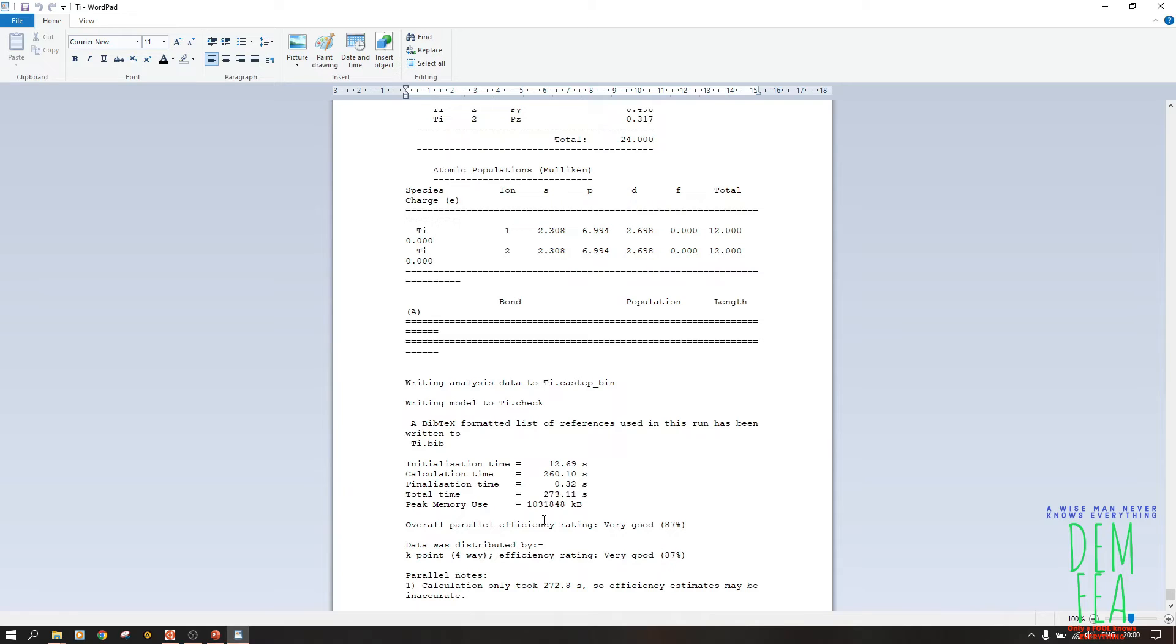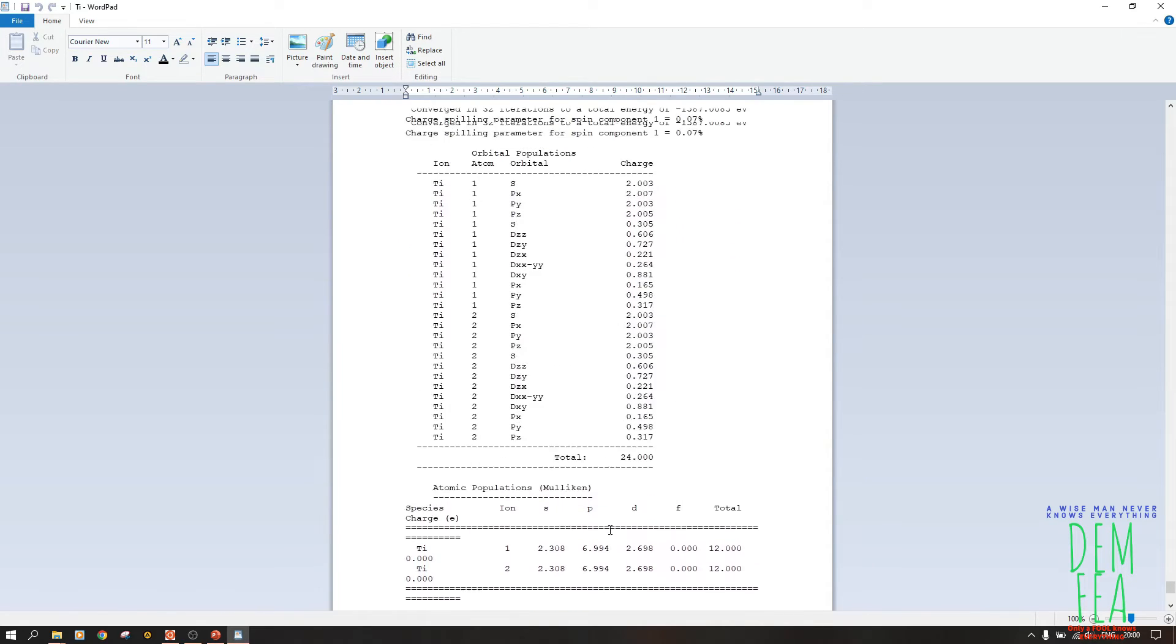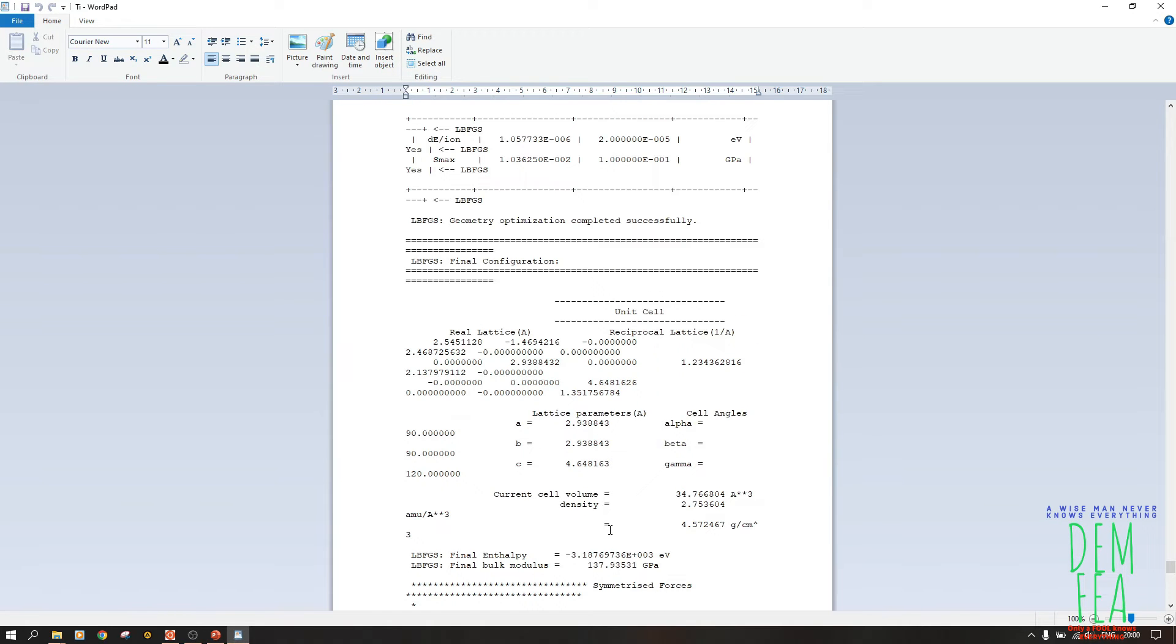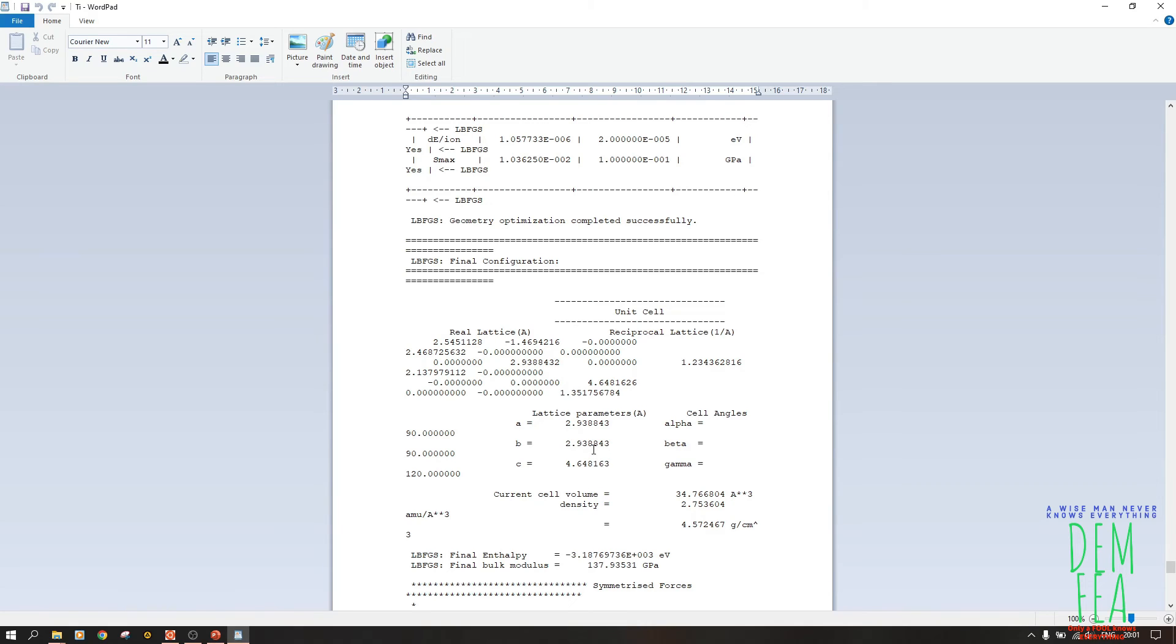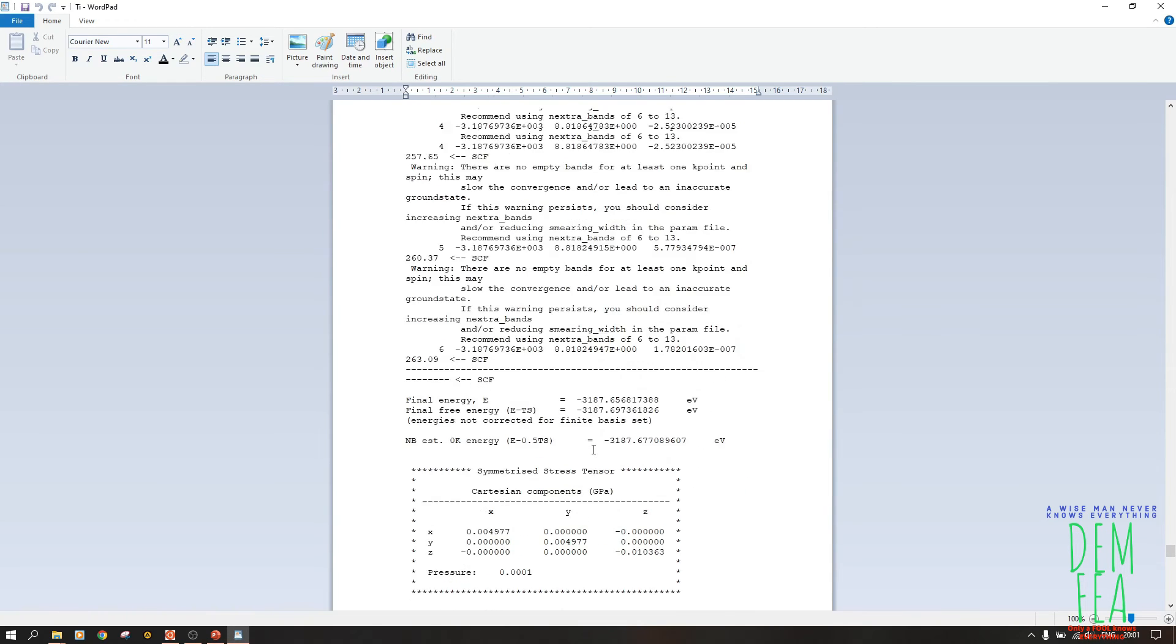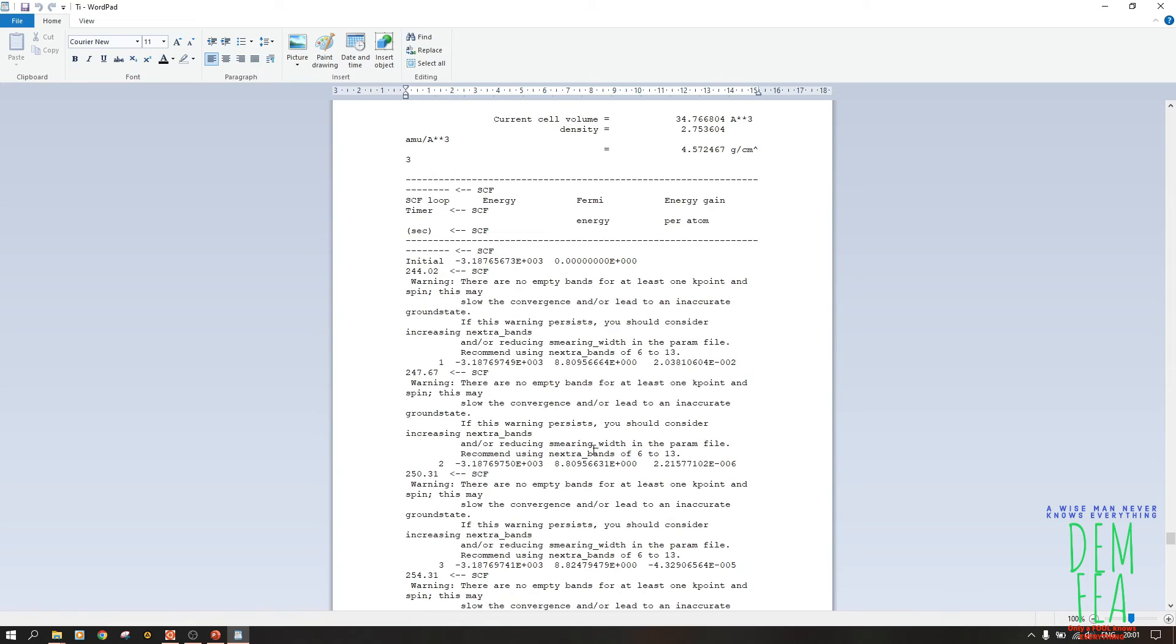We want to see now the lattice parameters. So we have 2.938 and 4.46. As you can even see, we have even the density of titanium is 4.57. As you can see, when the GPa is given here, the density is almost as close to pure titanium, which is 4.5. But we'll see how we can improve these lattice parameters because the one for pure titanium is 2.95 and this one is around 4.68 something. So we are going to do some calculations later and see how we can improve this accuracy to as close as possible to the commercial purity titanium.